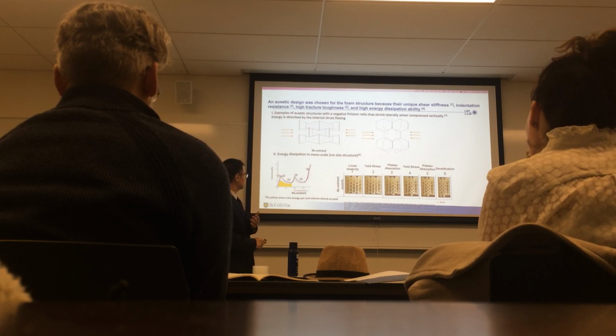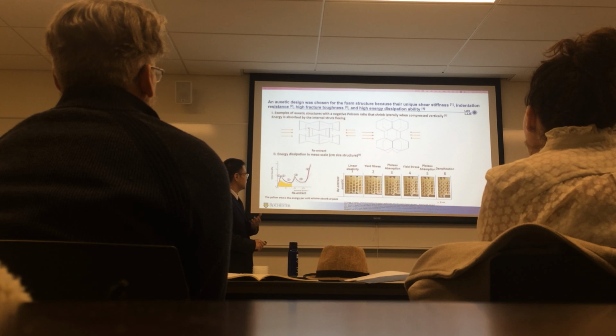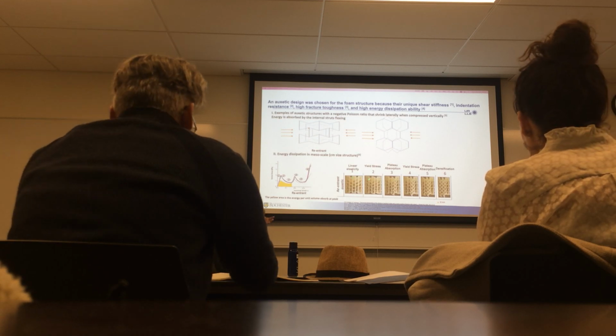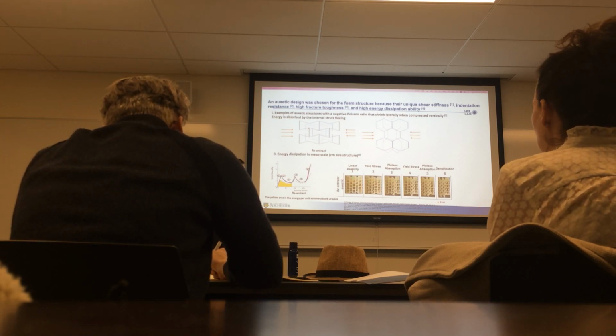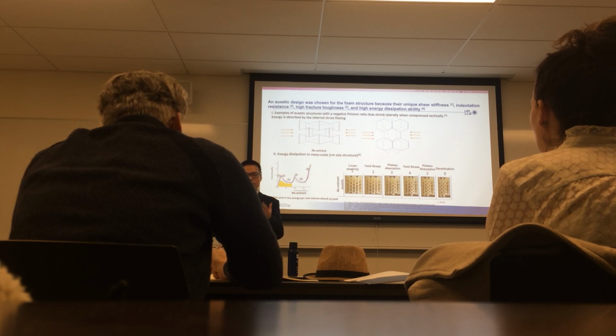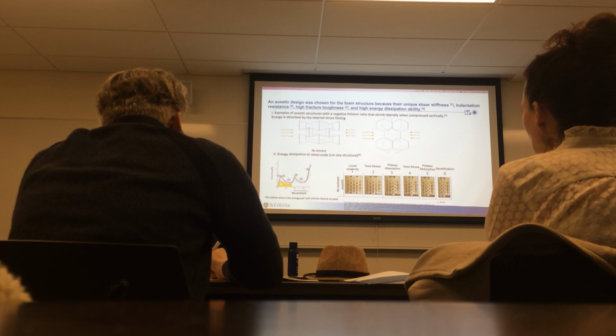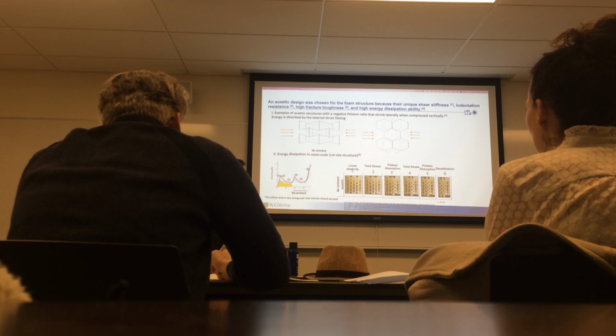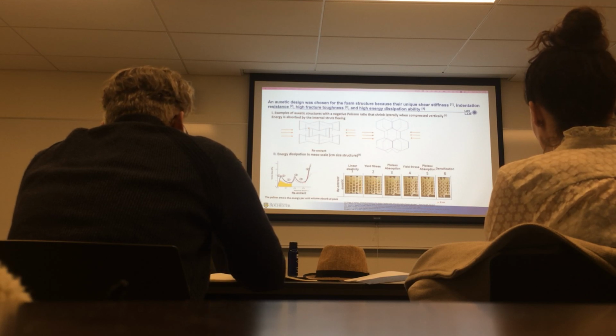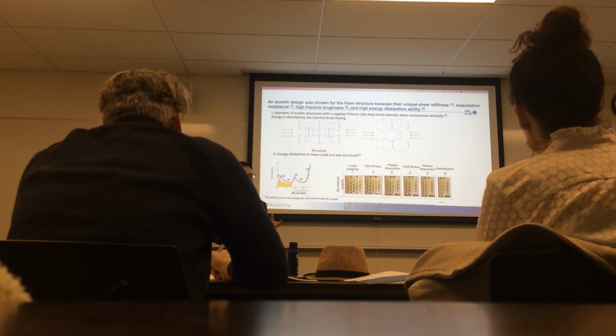After point 2, it's zero stress, and the foam structure reaches the plateau absorption area. If the foam structure is to absorb more energy, it needs more strain in the plateau absorption area, until the foam structure reaches the densification part, which means the foam is crushed.